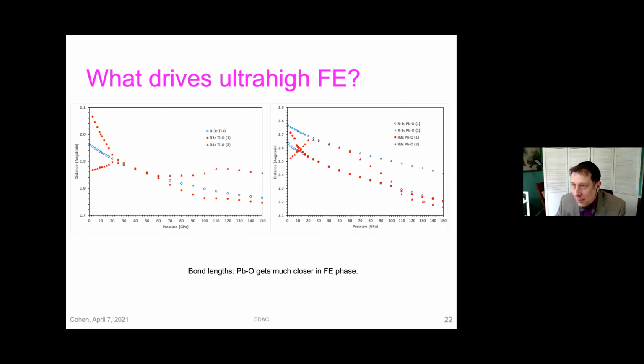So it's in fact verifiable with the X-ray single crystal diffraction. The thing that's not verifiable, as I understand it, in X-ray diffraction is whether you actually have a polar or a nonpolar structure. But once you take a model of a nonpolar structure, you could refine it, and you would get these positions, right? If the quality of the data would be sufficient, we shouldn't need to assume the structure. We should get it from the diffraction. Well, this is an interesting task. Thank you.